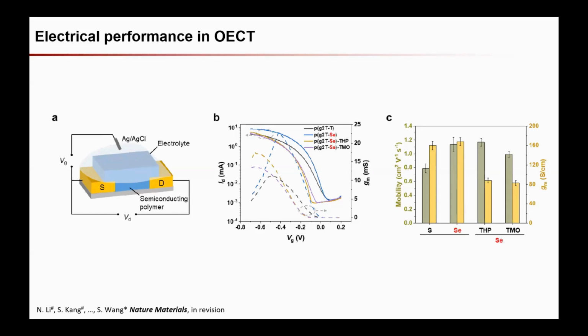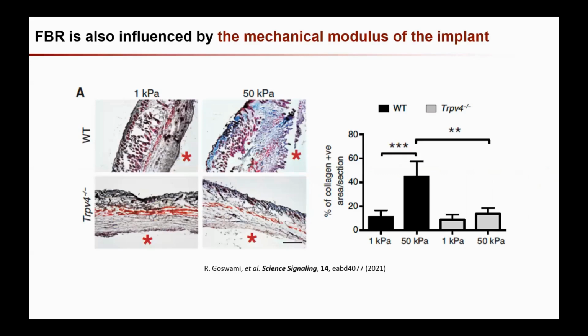But the chemical property is only one aspect of foreign body response. Mechanical property is also very important. For example, in a previous immunological work, people have shown that for hydrogel, if you vary the modulus between these two levels, both already very soft, 1 kilopascal and 50 kilopascal, and then do the same kind of implantation experiment as we did.